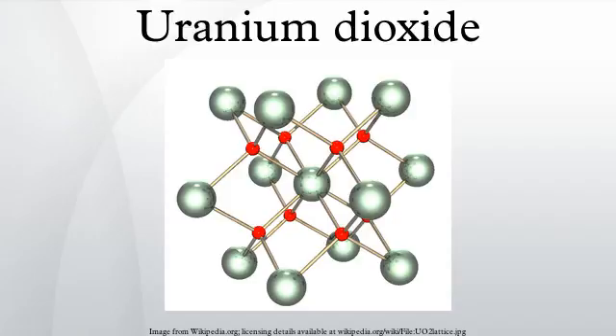Uranium dioxide is carbonized in contact with carbon, forming uranium carbide and carbon monoxide. UO2 plus 4C yields UC2 plus 2CO. This process must be done under an inert gas as uranium carbide is easily oxidized back into uranium oxide.